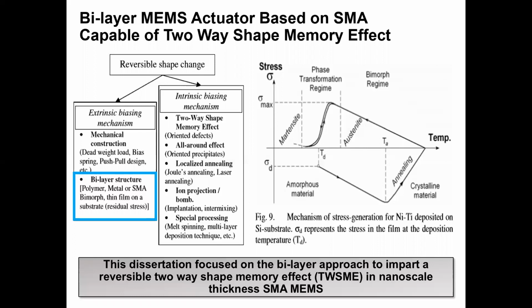The graphic on the right-hand side shows how the typical film stress in an SMA film changes as a function of temperature. And this is as the material is cycled between the martensite and austenite phases for a nickel titanium film on silicon substrate. The process would be similar for a released SMA-MEMS actuator, where these reversible deflections can be imparted due to the shape memory effect.